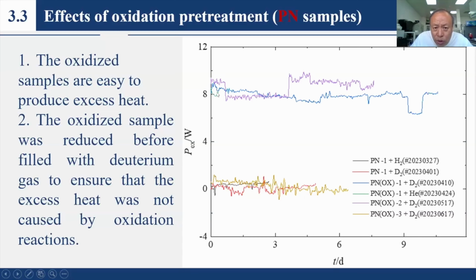And then we used helium. The green curve, the short green curve here, is for a short time. There is also excess heat. It means excess heat did not disappear using the helium gas. Then we used the deuterium gas again. We can find the excess heat existed for 1 week. One month later, we did the experiment again. This time the excess heat disappears.